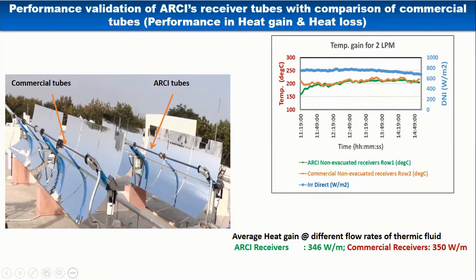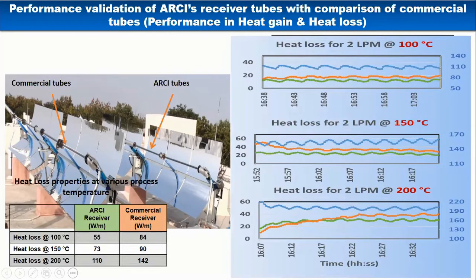In the case of the heat loss property, we can also study the heat loss of the actual receiver by heating the thermic fluid at different process temperatures, 100 to 200 degrees centigrade. We can calculate the heat loss using Q equals mass times Cp times delta T. So we could easily get how much heat loss we observed in our tube and the commercial tube. When compared, our heat loss is very low compared to the commercial one. That is because of the lesser layer thickness and the high stability in open atmospheric condition.